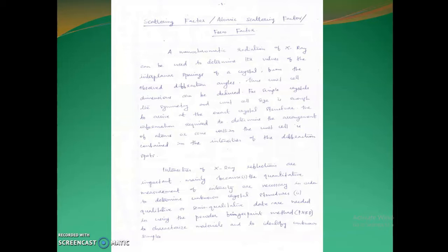to learn it. Okay, so as we have already discussed, we use X-ray diffraction techniques in order to determine the crystal structure, right? Monochromatic radiation of X-rays is used, and by applying Bragg's law, Bragg's equation, n lambda equals 2d sine theta, we can determine the interplanar spacing d, because the lambda value is already known depending on which X-ray source we use. For example, if we use a copper source, the value of lambda would be 1.5418 angstrom.